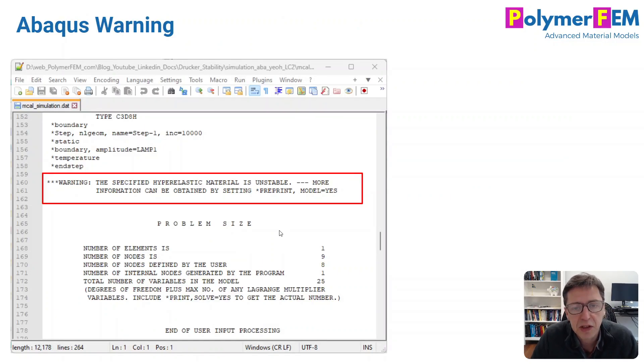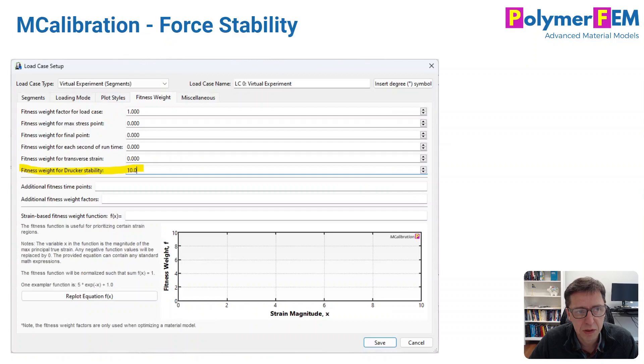Another thing to keep in mind is that your finite element program may warn you about this. This is the warning that Abaqus provides if you plug in the exact material model that I had on the previous page. This says the specified hyperelastic material model is unstable, and that's good to know. But it's in the DAT file, and not everyone reads this very carefully. I also tried to run a test case with Ansys, and I didn't see this warning. So if you can tell me where to find it, let me know, but I didn't see it. So perhaps Ansys doesn't even warn you about this unless you ask it in a specific way. So that's something to keep in mind too.